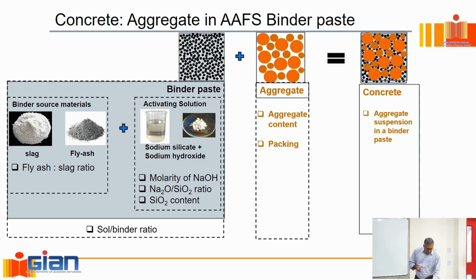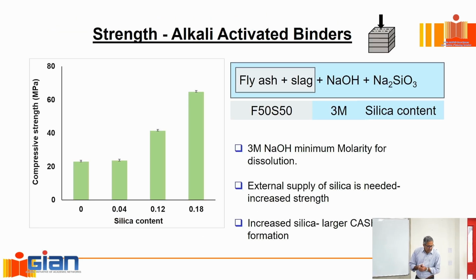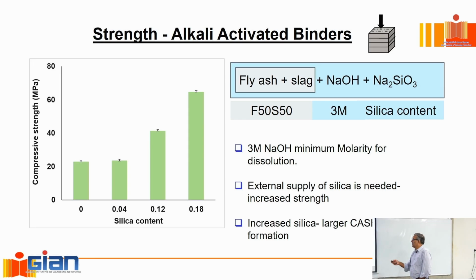Now, the first thing is, why do we add this sodium silicate? Like I said, and what does sodium silicate bring into the picture? Well, if you look at fly ash and slag, these are my source materials. They're bringing in silica, but there's not adequate silica. So to supplement it, I add sodium silicate. Now, what happens when I increase the silicate content? What is silicate content? It's the amount of silica present in the solution made up of these two.